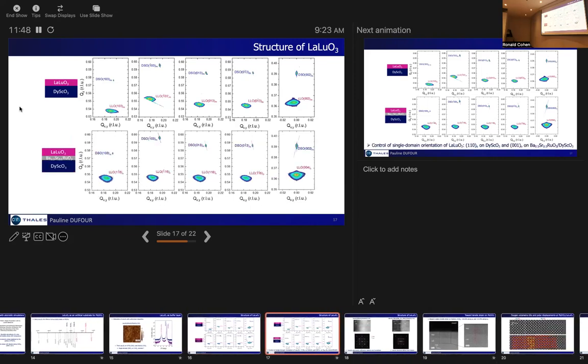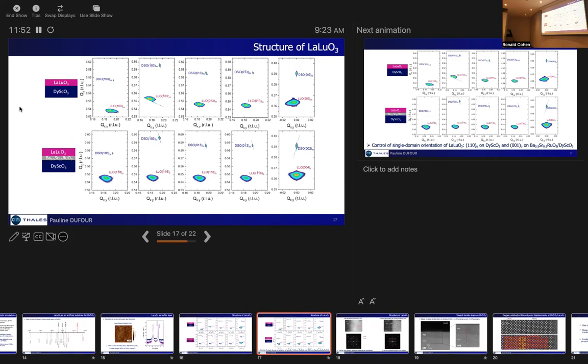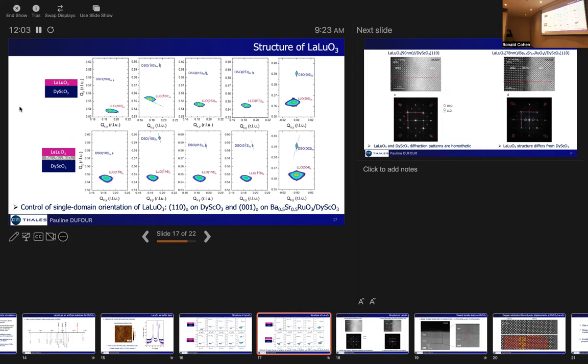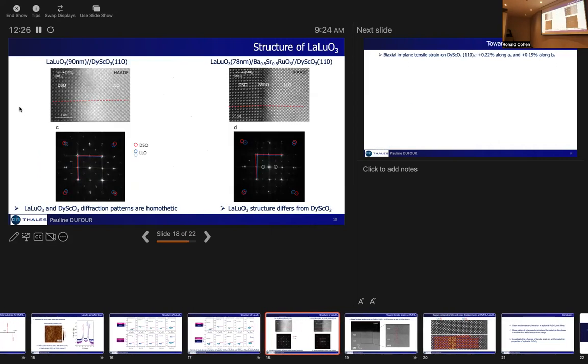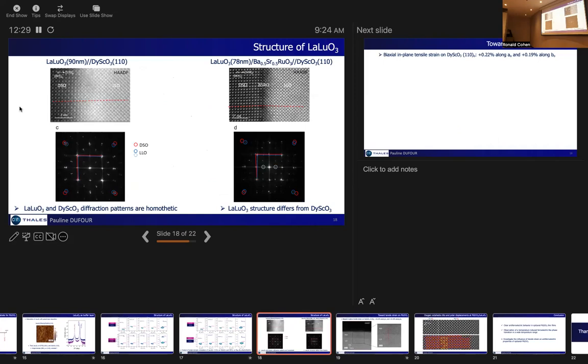Interestingly, also, if you insert a spacer layer such as barium strontium ruthenate on DSO, you will see that it kills the symmetry conforming of LLO on DSO, and that this time LLO will adopt the same 001 symmetry as we have seen on STO. So just to summarize, directly on DSO, LLO is 110 oriented, and when it's grown on STO, or as soon as you integrate a spacer layer of BSRO, you will obtain the 001 orientation. So this is particularly interesting because it means that we obtain a buffer layer with relaxed films, and you can tune their orientations.